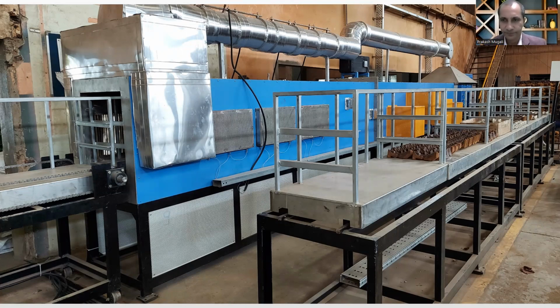And regarding the curing time? Depending on the size of the core, it can vary from 10 minutes to about 45 minutes. It can be adjusted by controlling the speed of the conveyor. Yeah, that's right, by adjusting the speed of the conveyor, the speed of the pusher. You can control the timing.